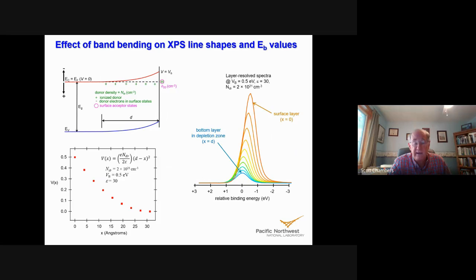There's actually the highest binding energy, and also if my depletion width is smaller than my probe depth, then I'm going to also see some layers that are below the bottom of the depletion width. So we'll have a bunch more peaks that do not change in binding energy because they're below the depletion width. But then I'm going to have all those different contributions to my measured spectrum. My measured spectrum then is going to have a different binding energy, a different width, and a slightly different line shape because of this band bending.